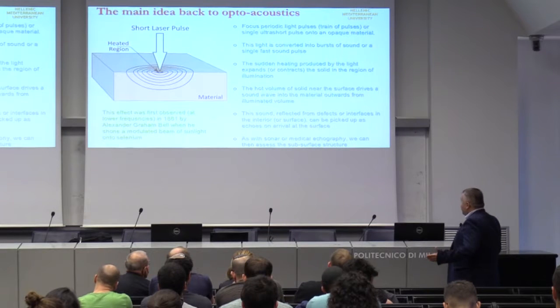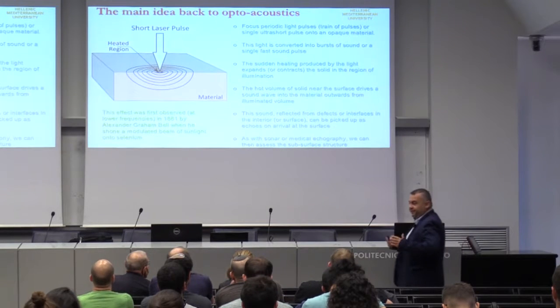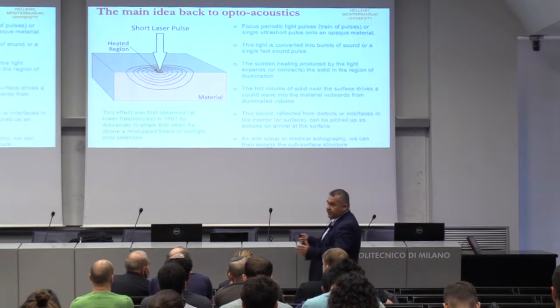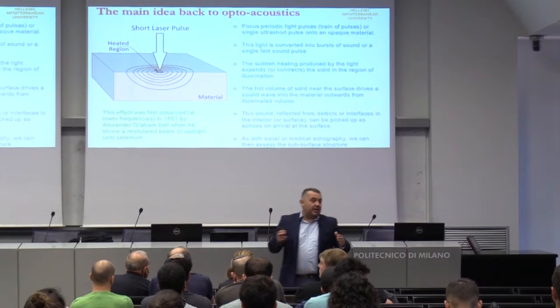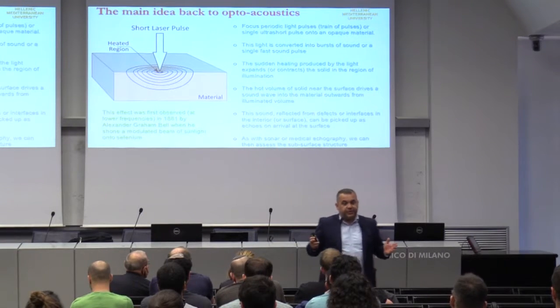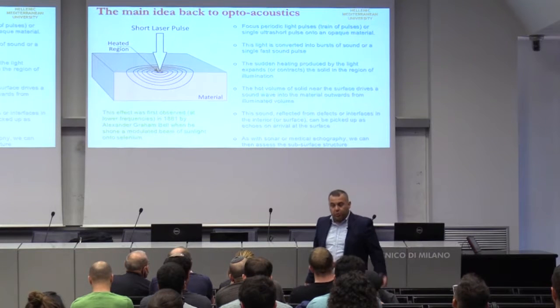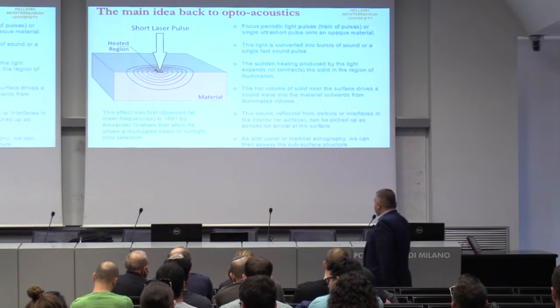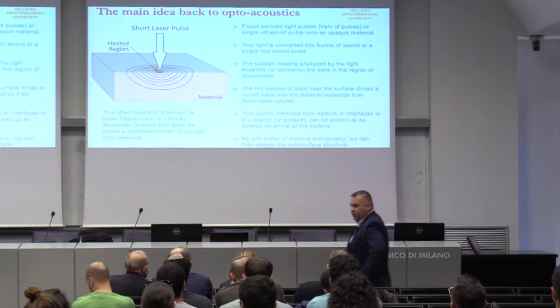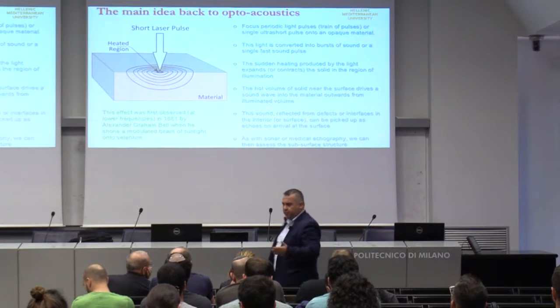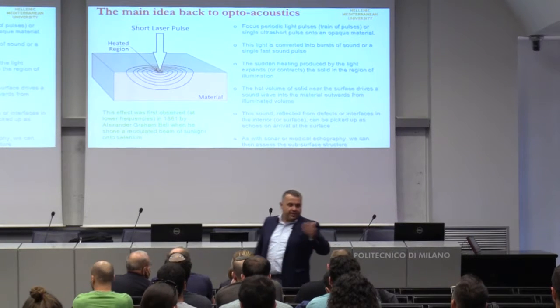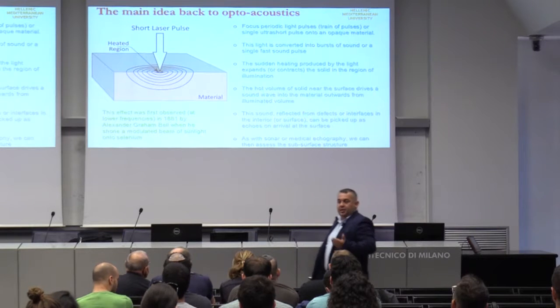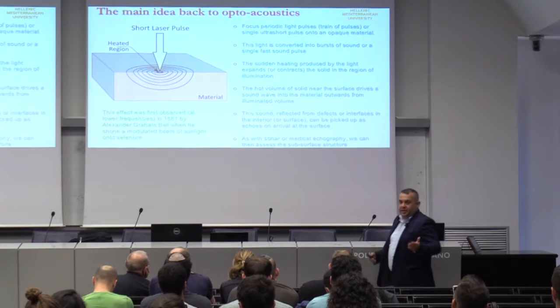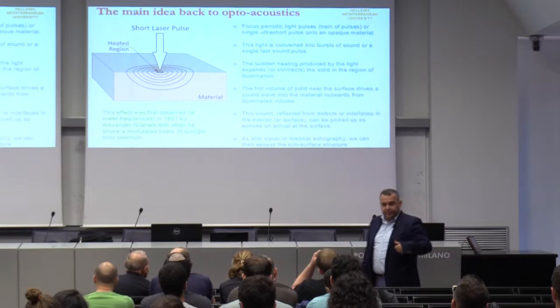So there is a sound which is reflected from defects, from interfaces, from all regions of the solid where there is different acoustical impedance, and arrives again at the surface, where we can probe it simply with another laser, for example, or another instrument, and do actually what I promised to you, the miniature sonar.